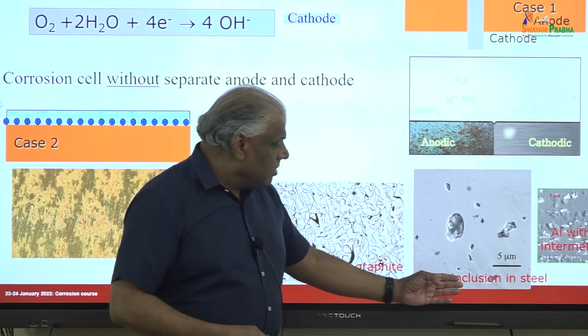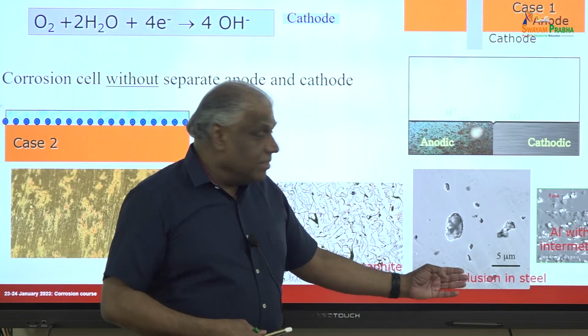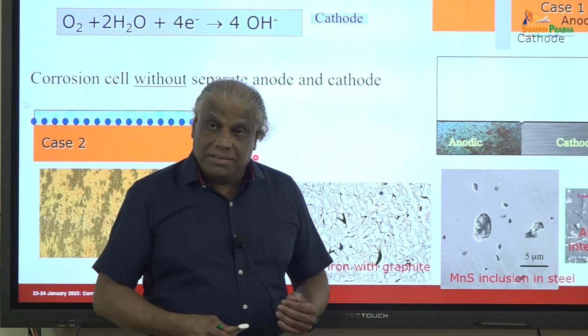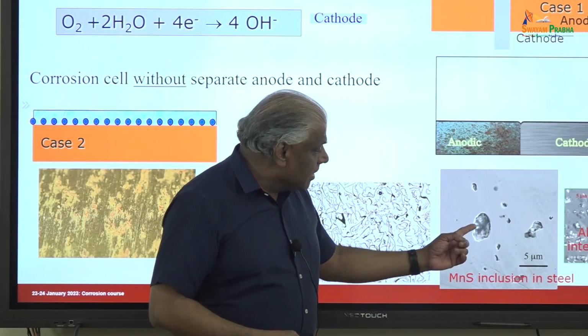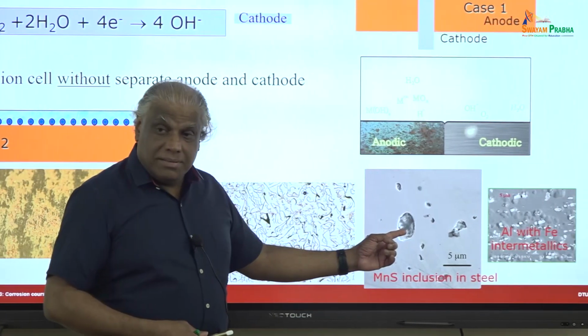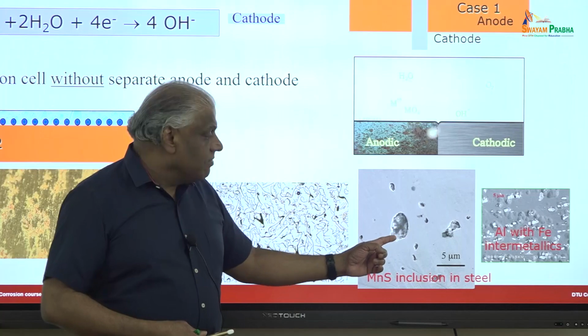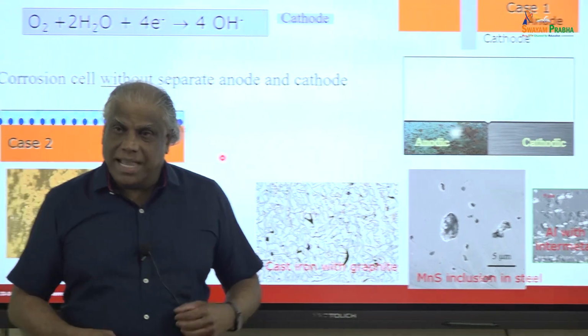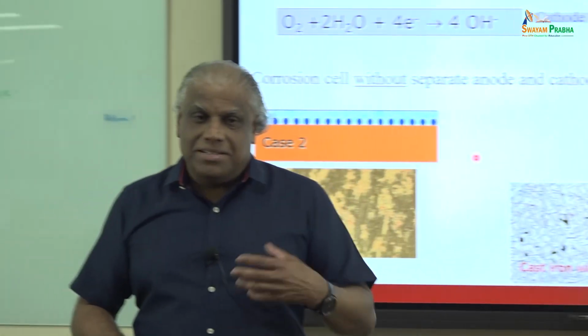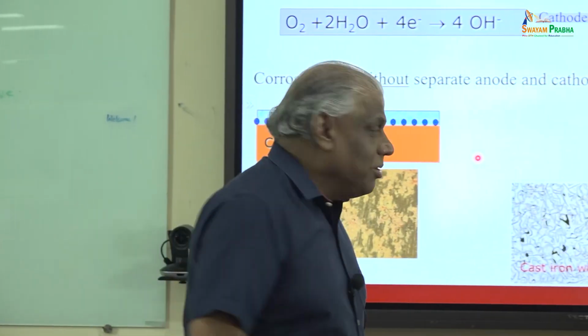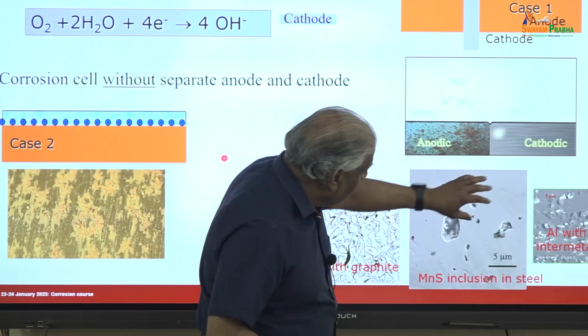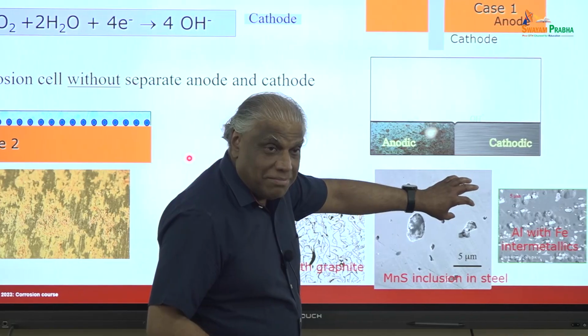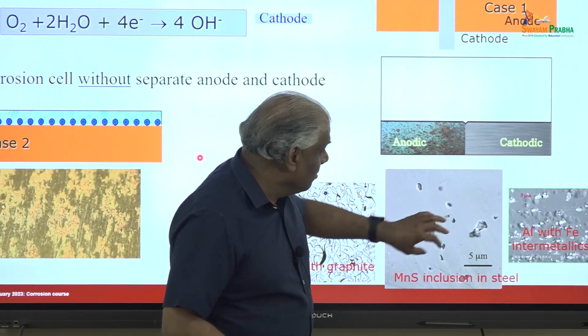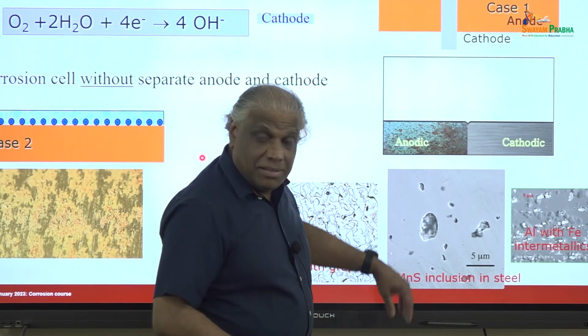Take the case of stainless steel. Why is the stainless steel corroding? There you can have the manganese sulfide inclusions in the steel part. This manganese sulfide inclusion is acting as a cathode, and the steel part is acting as anode. So the cathode reaction will take place here, and at the anode the metal will dissolve here. This will corrode, this will act as a cathode.